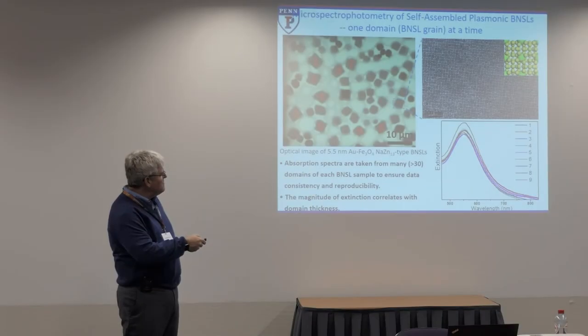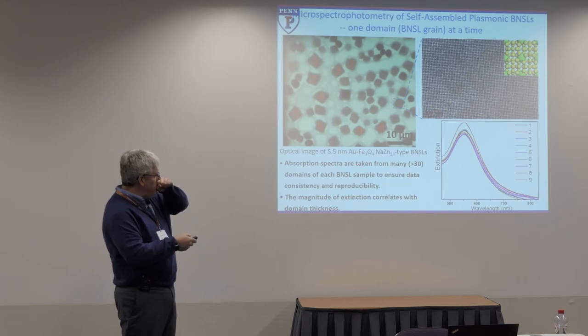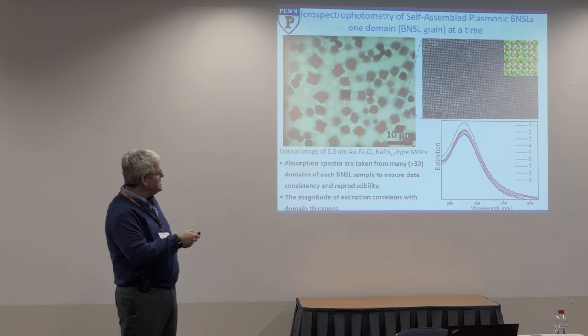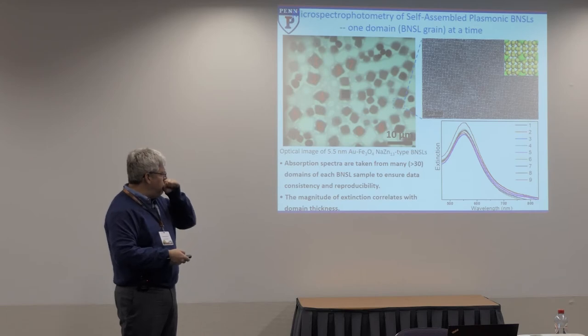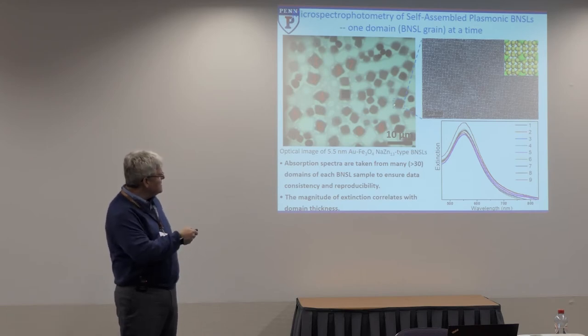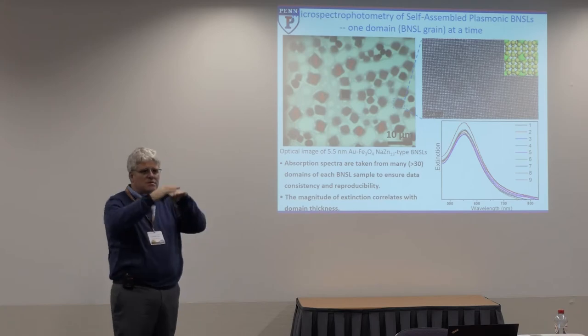You basically have to map all the sample optically and then go back to select reference points and do the electron microscopy. The positions that you see here are the position of a plasmonic resonance that's shifted away from its normal parent value because it's coupled; in this case the iron oxide is changing the coupling between the neighboring gold. The position of the resonance is almost identical between all these different islands. The only thing that's changing is the amplitude of the resonance, and that's because there are different numbers of layers in the island. So our goal here was to try to understand, as those nuclei grow, is there really a lot of heterogeneous broadening from structure to structure, or do they all really have a response where you can describe it as being representative of the underlying architecture?